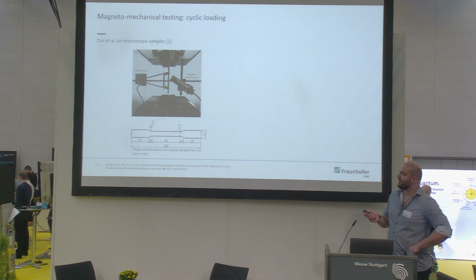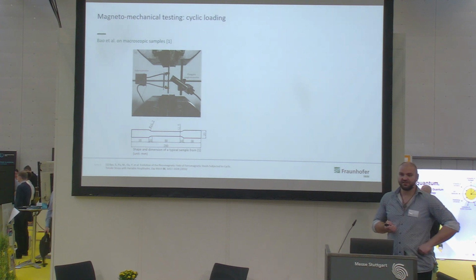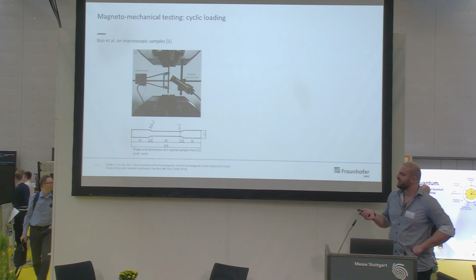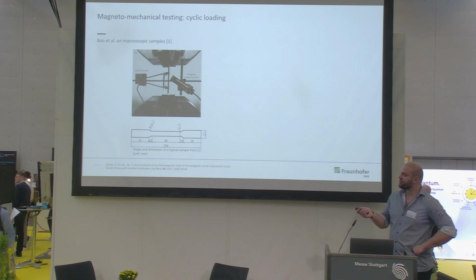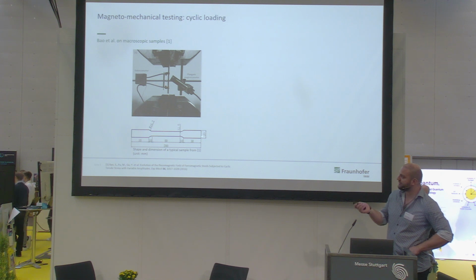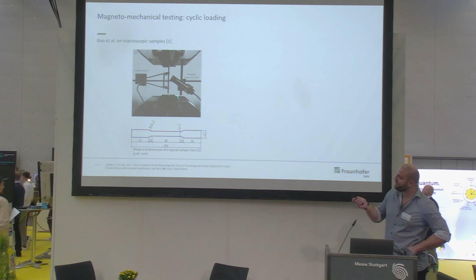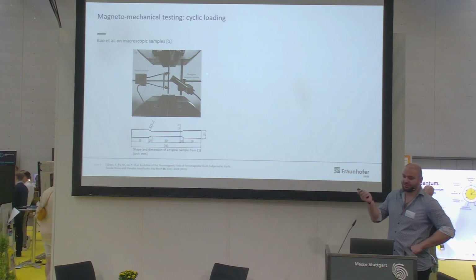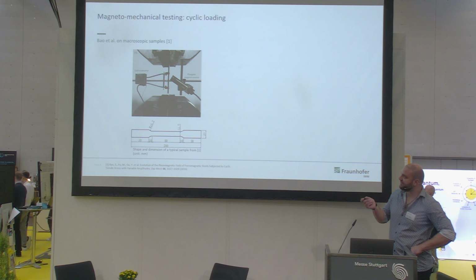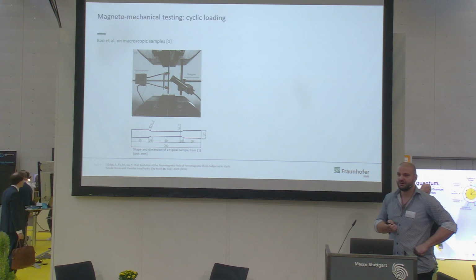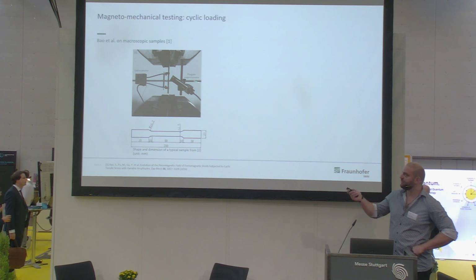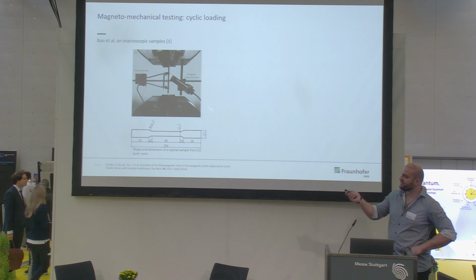There's a group by Bas et al. who do this very extensively. They have a lot of papers on these topics, and they typically use material samples which are quite long. These are 20 centimeters long and 2 centimeters wide. You can see this sample clamped in the middle of these two poles. They measure the extension with this extensometer, and the magnetic field is measured with a classic sensor, a so-called flux gate, which is aligned here on the side.